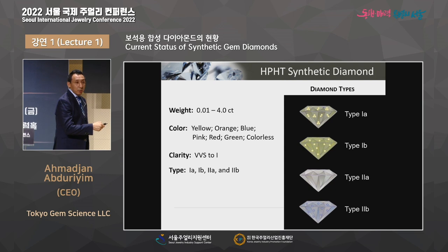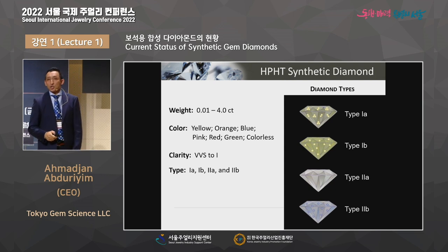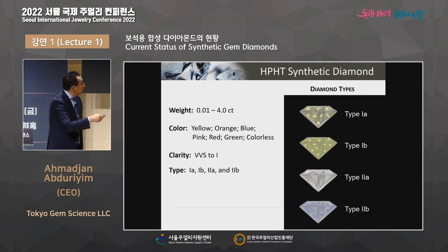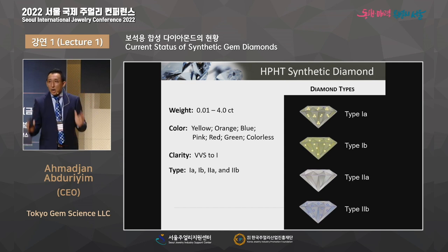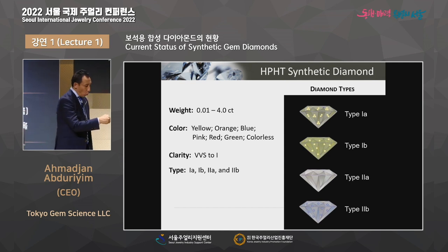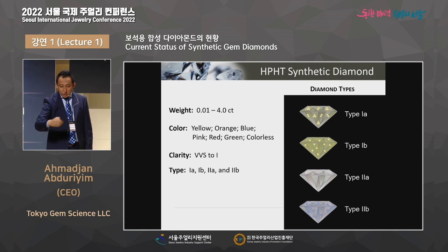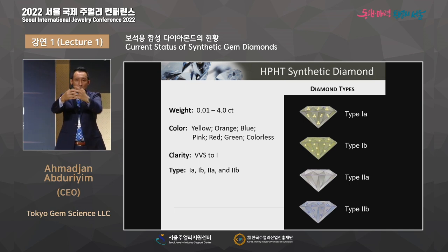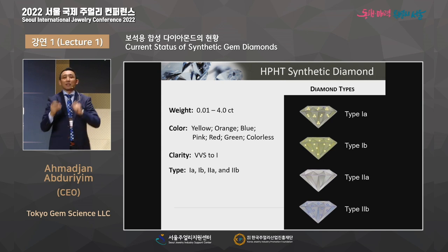First, if the diamond includes a minor amount of nitrogen, one nitrogen replaces one of the carbon atoms to form this yellow. Natural diamond also starts as this type 1B, under the earth. So synthetic diamond also starts with the same process. And gradually, when you heat up, the nitrogen can get together, aggregate, to form 1A. The color becomes lighter. So where we see 99% of natural diamond is like this type, synthetic diamond is majorly 1B.